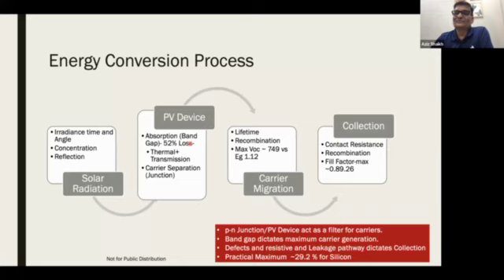Okay, that never stops. So the junction acts as a carrier separation. Then once you have these carriers generated, they have to be collected. So they have to migrate to the collector, and that's where the lifetime of the carrier matters. If the silicon has an original defect in terms of the wafer, either you create vacancies, you create inclusions, or you have a stacking fault, all these defects have charges associated with them. So if a carrier goes there and it is a charge defect, it is going to just neutralize it.